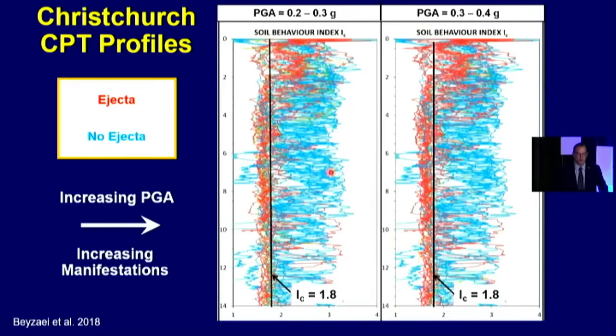If we notice that the red are sites that exhibited ejecta, and the blue are the sites that did not exhibit ejecta, what we see is all the sites at these levels of acceleration that had ejecta were thick deposits of clean sands that had soil behavior type indexes less than 1.8. The other sites went back and forth. They were highly stratified soil sites that had some layers that liquefied, but they were surrounded top and bottom by soils that did not liquefy or restricted flow.